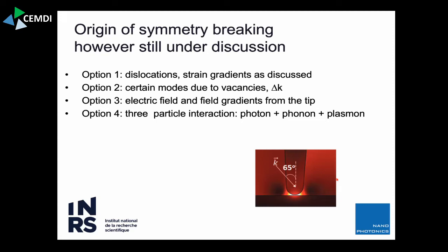So the last option, which is really relatively recent, is that a couple of theoreticians predicted that, well, this kind of spectroscopy you do there is, strictly speaking, not standard Raman spectroscopy. Standard Raman first order means you have one photon interacting with one phonon. And for that matter, you have rules of preservation of momentum, but you have this plasmon resonance sitting on top of your tip, and the plasmon actually kicks in its own momentum. So that in principle, you have a 3-particle process. And for the moment, experimentalists are still shopping for appropriate material systems to verify this, whether there is actually an effect there.